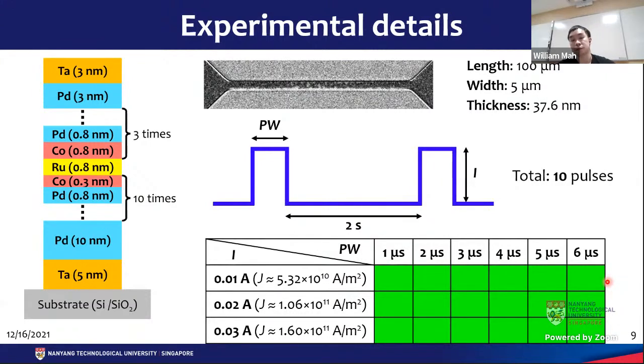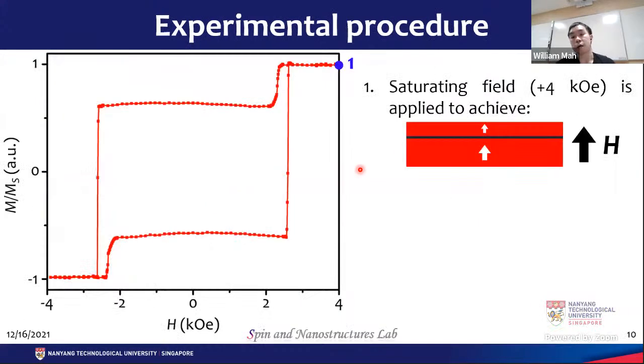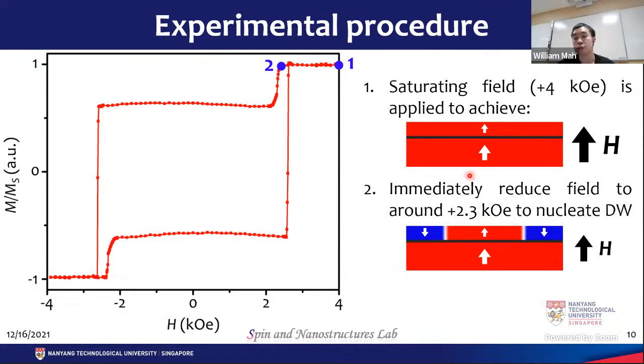So before that, the first step is to apply a really strong magnetic field in the plus Z direction so that I can saturate the entire system. Then I immediately reduce that field to around 2.3 kilo oersted, still in the plus Z direction, because at that field, I can nucleate domain walls in the free layer, the top free layer. And after that, I will apply current pulses and observe what happens to the domain wall under Kerr microscopy.